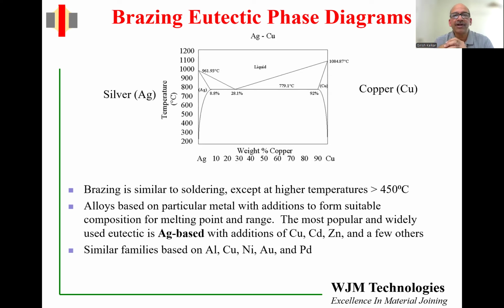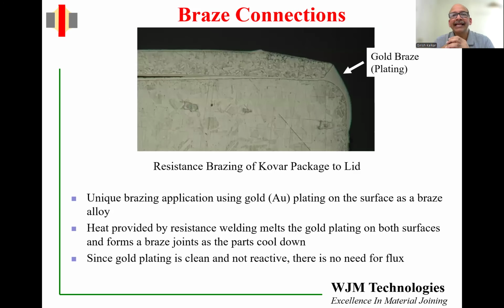Most of the braze alloys, as I mentioned, and solder alloys are based on eutectics. That means you are using a mixture to reduce the temperature and then adding a few other things. But that's not always the case. There's always an exception to the rule, and this is a good one. Here we have a resistance brazing application where we are brazing a Kovar lid, about a millimeter thick, to a Kovar electronic package. Both components have gold plating on them, and this is pure gold. It's not a eutectic mixture. The gold is already plated on there, so you're not adding it like a foil or a paste. And because gold is clean, it doesn't even need a flux. So gold is very unique as a brazing alloy in that sense. It is plated, it is not a mixture, and it does not need flux.